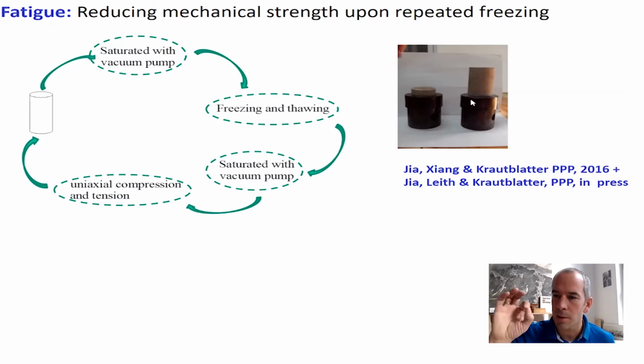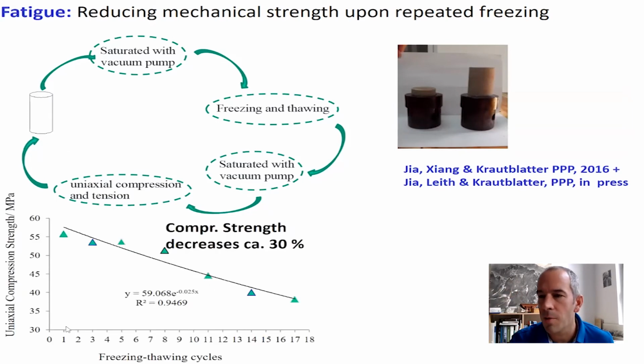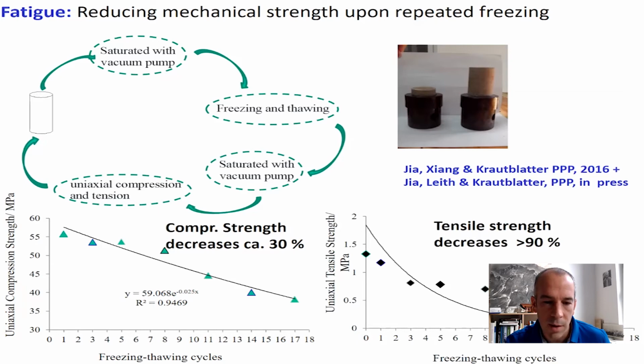We took a lot of samples, we froze them, and after every freezing, we took 2 out of them and tested how they mechanically perform to see how tired they get, how the fatigue proceeds. And you see over 18 freezing cycles, the compressive strength decreases by 30%, and the tensile strength decreases massively in 17 cycles. So after 17 cycles, you can take the sandstone and pull it apart manually because the tensile strength is so susceptible to that.